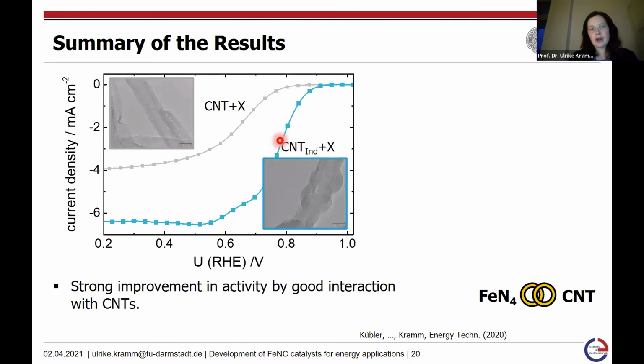In the first comparison, we compared the activity of the surface-functionalized CNTs with the X, which stands for the iron and additional nitrogen precursor that was used within the preparation of the catalyst material, in comparison to just CNTs, again, of course, plus the iron and nitrogen precursor.